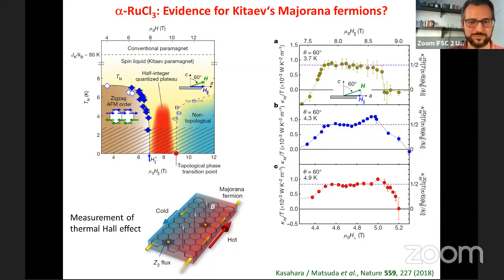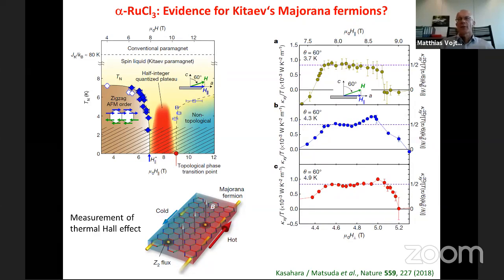That's a difficult question. And I guess one needs to go one step back when discussing this. First of all, the explanation which I gave you was oversimplified, because what I said is you get this quantized Hall effect if there is heat conduction by edge modes. However, we have to keep in mind that we talk about solids, and there is always bulk heat conduction by phonons. And that makes this very, very different from the charge Hall effect. I mean, the charged Hall effect, like the conventional quantum Hall effect, there the bulk is really an insulator, and there is charge conduction exclusively by edge modes. This is something which with heat you can never achieve in a solid, because there's always phonons.